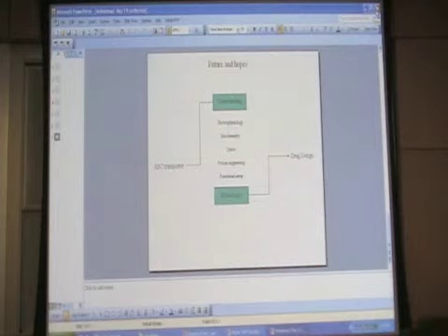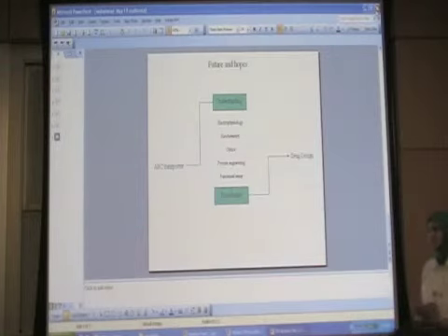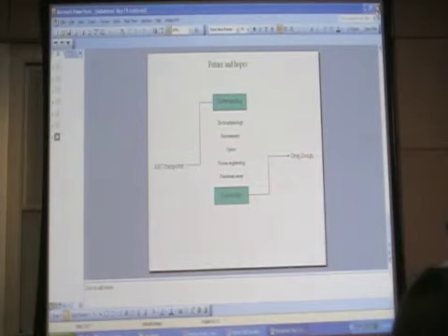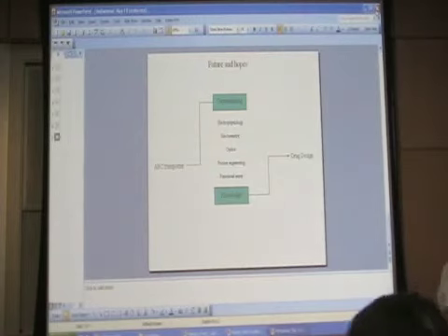Well, we make windows of silicon nitride that are 30 nanometers thick. It's convenient to do so. We put them on a silicon substrate, grow them, and then take away the bottom silicon. We have a nice 30 nanometer thick window. So we drill it with an electron microscope. It's convenient, that's it.